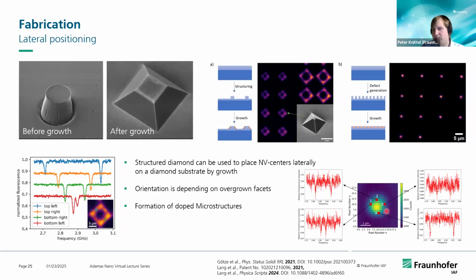And what you see here is these positioned NV centers after the growth. And here is a measurement. This was also done in the wide field system. That's why it's quite noisy, but you can still see, even though this spot is the size of a micron, a bit smaller, that even on this very small structure you get preferential orientation in these grooves. So maybe this is an approach for placing single centers on a micron, maybe a few hundred nanometer level, but this is at the moment under investigation.